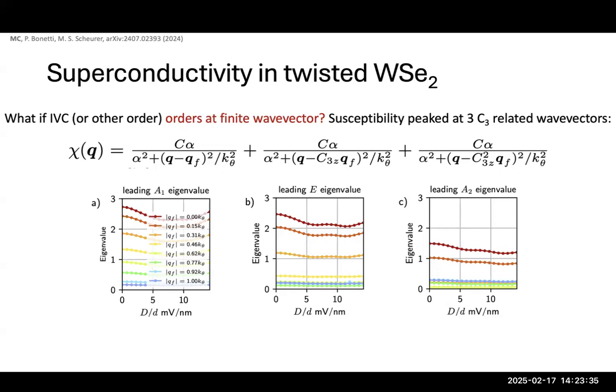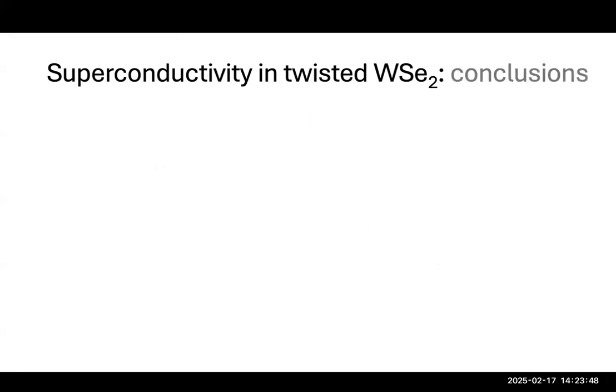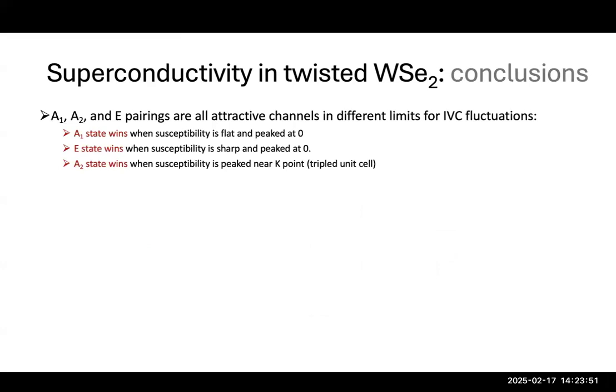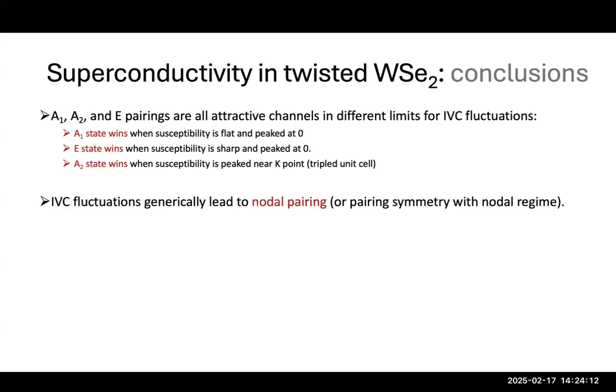And what we find is that the leading instability in the case for this 120-degree antiferromagnet is the A1 state. So in this regime, we find the last state we considered to win, and again, it's the nodal version of this state. So the high-level conclusion is that there's competition between all these states which now have sign changes. And they all have an attractive channel in different limits for these IVC fluctuations. So the A1 state wins when the susceptibility is more flat. The E state wins when it's very sharp and peaked at 0, and then the A2 state wins when you have ordering at finite momentum.